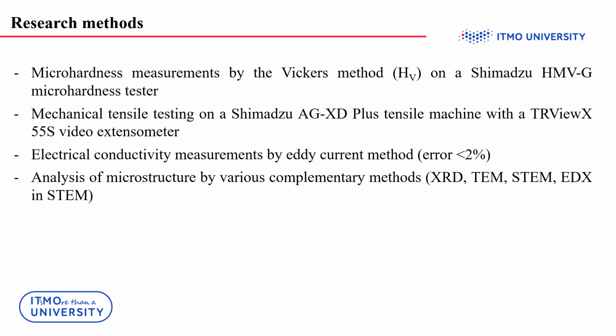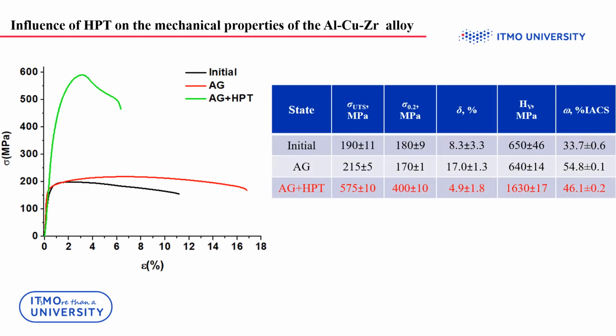Mechanical properties were measured by conducting uniaxial tensile tests and microhardness measurements. The electrical conductivity was measured by the eddy current method. The study of the microstructure was carried out by various complementary methods. Conducting HPT led to a dramatic increase in strength characteristics.